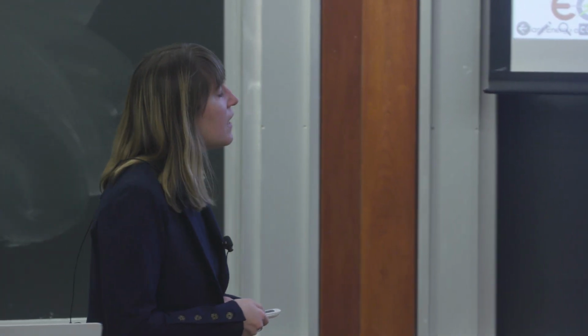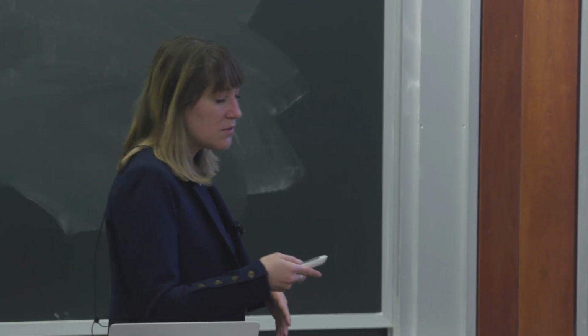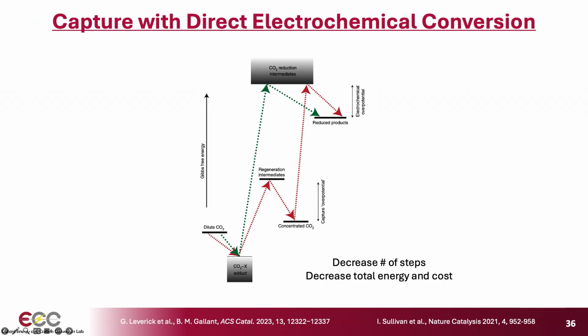And CO2 electrolyzers have relatively high cell voltages, and they're also energy-intensive processes. And so the point here is that the energetics of this and the energy requirements of the upstream separation accrue. And so there's been great interest in looking at whether we can actually avoid this intermediate regeneration step entirely. And the benefits are summarized in this energy schematic shown here. So rather than having to regenerate and then concentrate and then go through this reaction to form product, perhaps using an electrolyzer, we can just directly capture the CO2, run an electrochemical reaction, and go straight to products without having to make the gas phase CO2 in between.